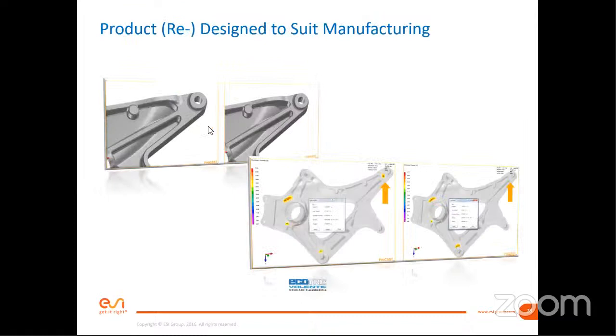So maybe just a very short case or example of this. You can see the part which was previously designed like this. The transition of the thickness was quite okay here, but the thickness itself caused the problem. Here, of course, we have some drilling, some machining after the process, and we can see that with the original design, it forms some porosity in the part.